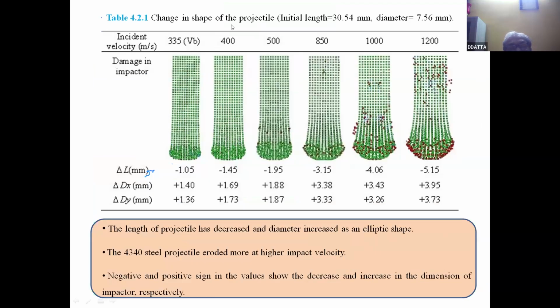Now, we have also studied the shape change in the projectile face. This is the change in length and corresponding strike velocity. Strike velocity means the initial velocity of the projectile. Here you can see that if it is 1200 meters per second, then there is a lot of deformation in the projectile head. I think this is the case of the blunt nose, and the circular blunt nose has got an elliptic shape. The 4340 steel projectile eroded more at higher impact velocity. That is expected. Negative and positive signs indicate decrease and increase.